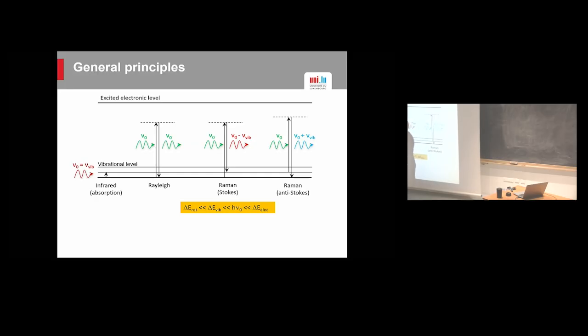And then it gets excited, falls back, and depending when it falls back, you have different processes occurring. If it falls back to the same energy, it's frequent but useless for us. So this is Rayleigh scattering, elastic scattering. If it falls back with an energy loss, it means that a phonon has been created in the process, and so this would be called the Stokes scattering, and this would be the anti-Stokes, where your system starts from here and falls on the ground state. In that case, there is a phonon annihilation in the process, and your outgoing light has more energy than incoming light. Okay?